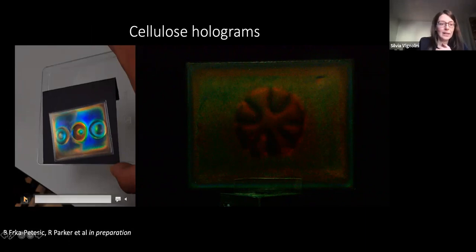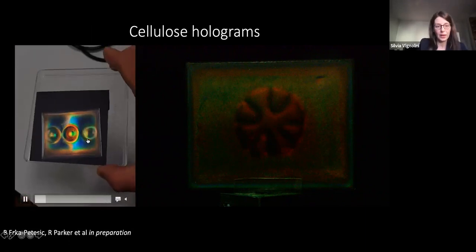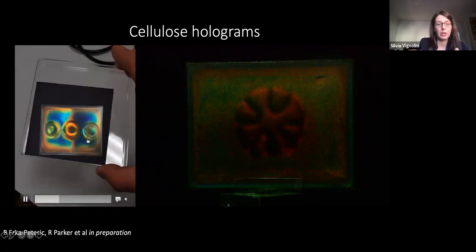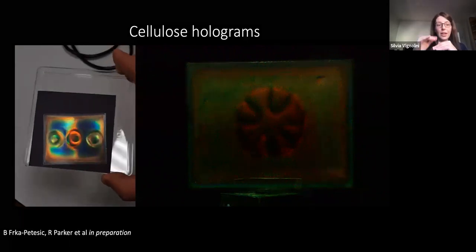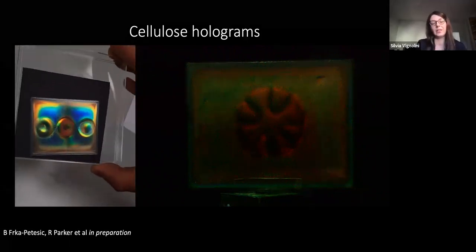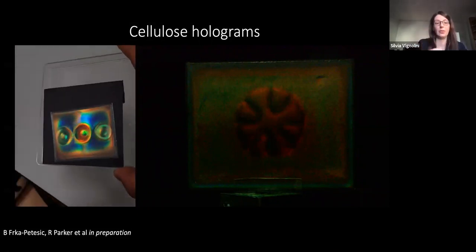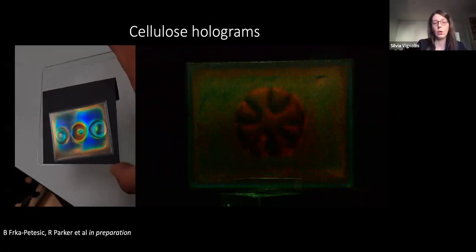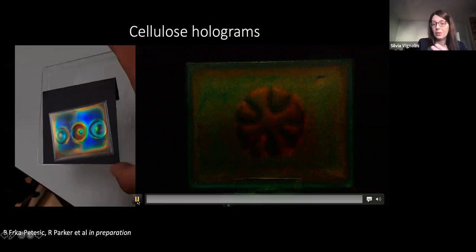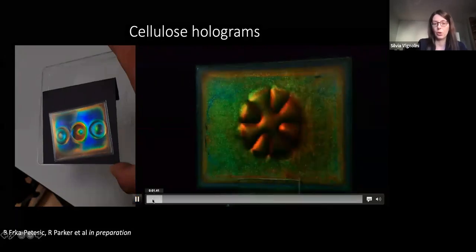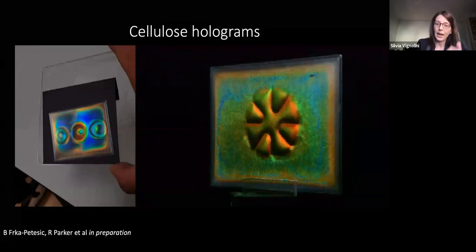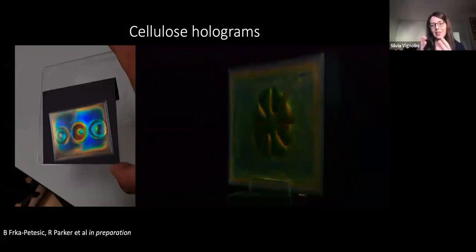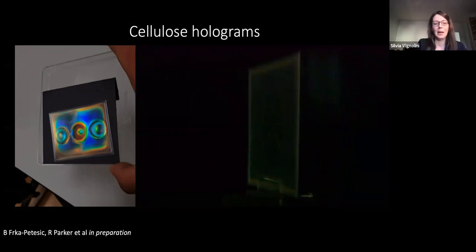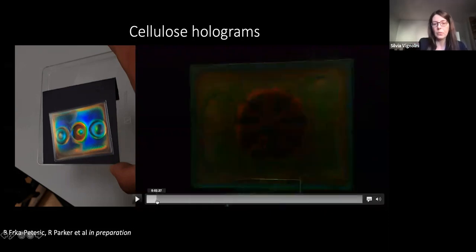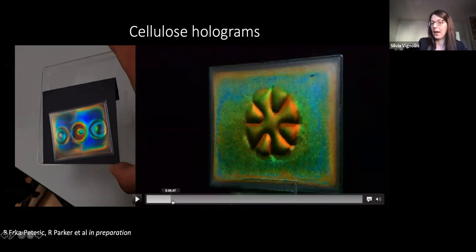So these are flat films where the cellulose film is perfectly flat, but since the orientation of this photonic structure is in different directions depending on the angle, you obtain this really nice three-dimensional effect. And this is another video that hopefully will show, yes, where you can actually see that the color has this three-dimensional appearance, while in reality it's a flat 2D film.